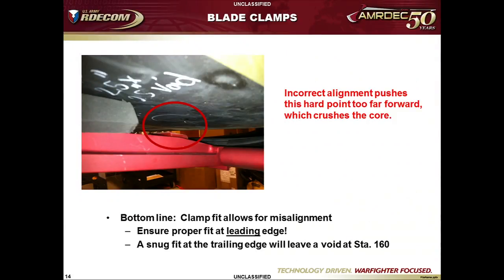By leaving that clamp down in the rear, when this gets pushed on from the back, especially if it's two soldiers standing up on top of the B1 stand pushing it on, they're going to push it all the way on until it hits the foam at the back. Because it's got foam, it's probably where it's got to go. Where we run into a problem, though, is now it overworks. When it's clamped up, you see in that little circle there's a hard plastic piece on this blade clamp.